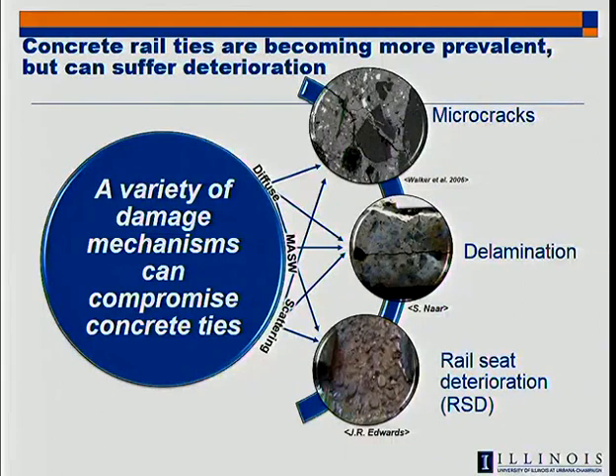No. We have a certain volume of cracking, and it's harder to quantify, and visually it's hard to see these cracks. I mean, you can think, oh yeah, I can see cracked concrete, but really, to differentiate between superficial cracking and extensive cracking, especially below the surface, it's very difficult to do. So in terms of concrete deterioration, that is one main focus, is breakdown. So freezing and thawing, delayed ettringite formation, which is a mechanism that concrete ties have experienced in the past because of processing. Alkali silica reactivity, also. There are cases of ASR affecting concrete ties that will manifest that way.